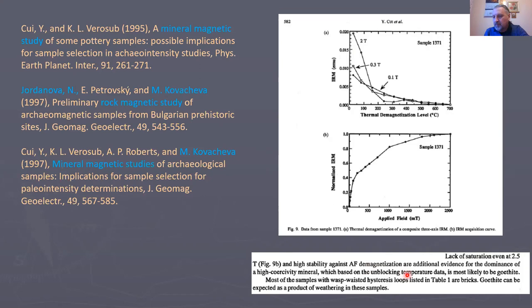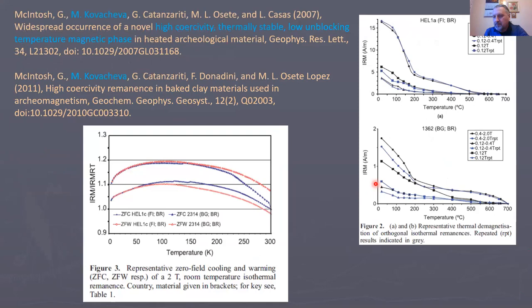So that's it. And it took another roughly 10 years before this phase, demagnetizing below 200 degrees centigrade, was recognized as a separate entity and called the high coercivity, thermally stable, low unblocking temperature magnetic phase by McIntosh and others. More recent studies have shown that this phase is very often seen in bricks, tiles, pottery, and so forth from many locations around the world.